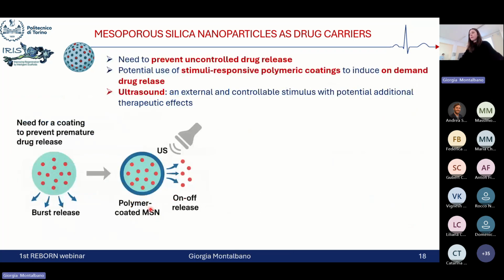But despite the great advantages and good properties of this material, if not properly engineered, this nanosystem can lead to an uncontrollable and burst release of the cargo. So in this case, we decided to engineer a stimulus-responsive polymeric coating to promote the retention of the drug and then its on-demand release. And in this context, ultrasound represents a very promising external stimulus because it is controllable, and we can also provide some additional therapeutic effects to biological tissue.